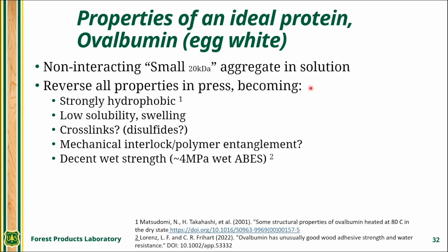But when you put it in the press, these properties reverse. Think about the egg, what I just told you about egg white, but you put that into a frying pan and you cook it hard, that is not water soluble anymore and has some strength to it, even when wet, as you will know from trying to clean your pots and pans after cooking eggs without oil. So the protein inverts and becomes strongly hydrophobic on the surface, low solubility. It still swells, but low solubility.